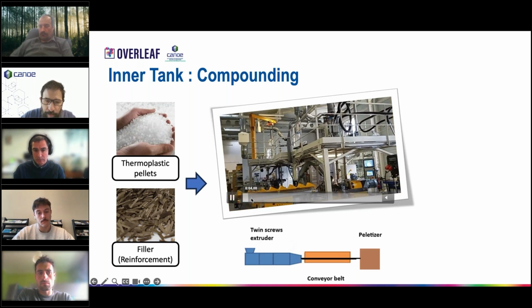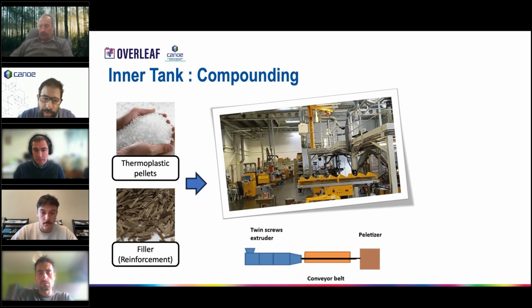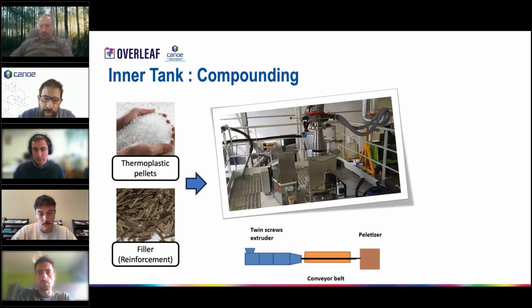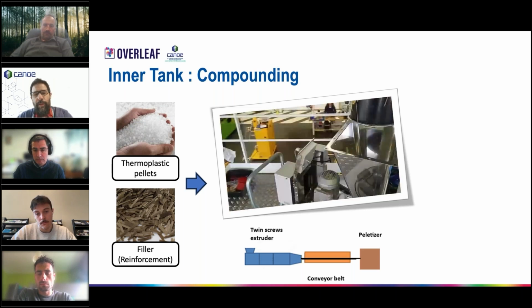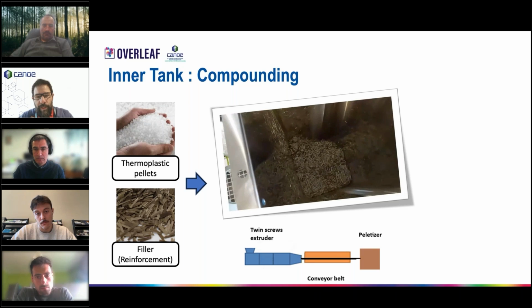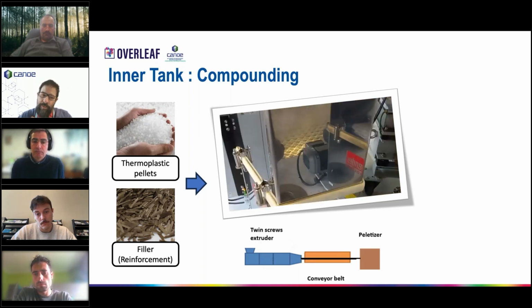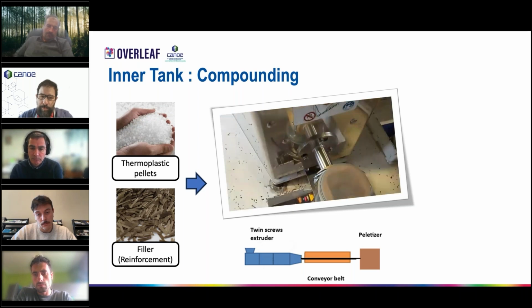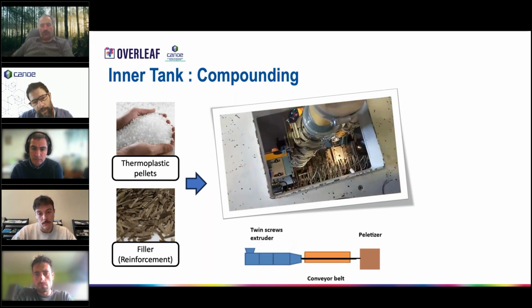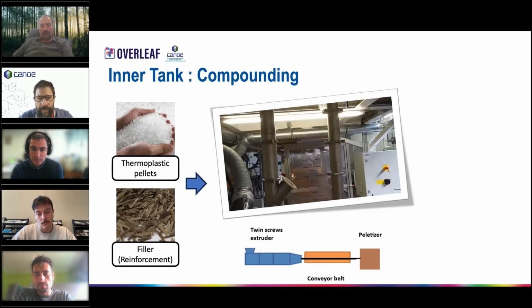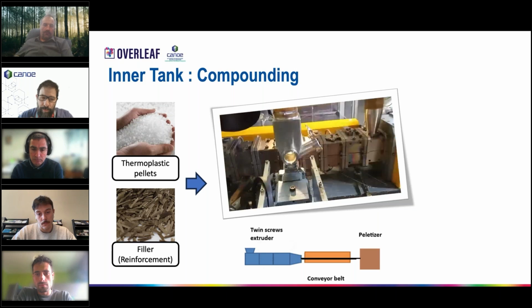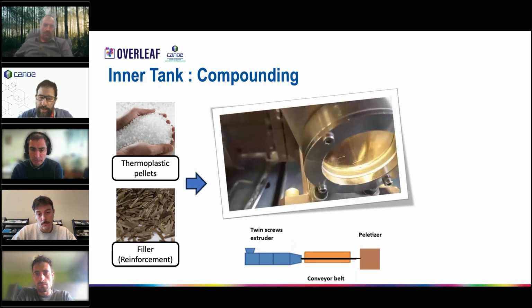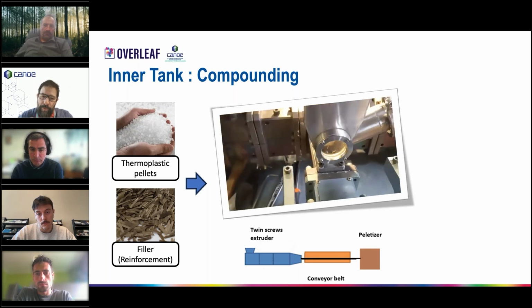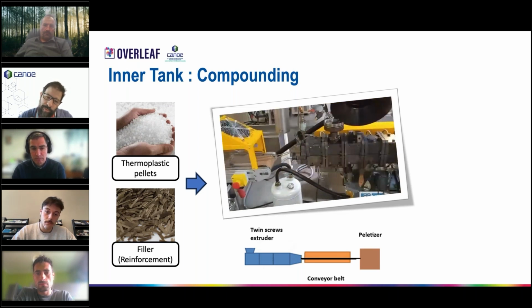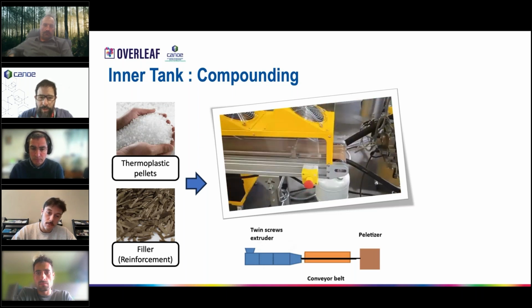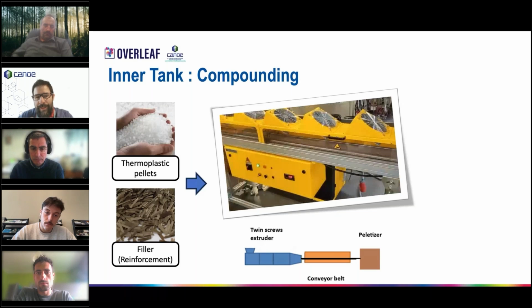So here you can see the room where Canoe is manufacturing all this material. Here we can see the dosing units, where we fill each dosing unit with a different material. Here it's the basalt fibers, and then you will see the pellets. The polymer pellets are fed into the main feeder of the extruder, on the right of the video, and conveyed by two screws, 26 millimeters in diameter. The fibers are then fed in the side feeders in order to blend them, melt them, and get a good homogenization of the fibers inside the polymer.